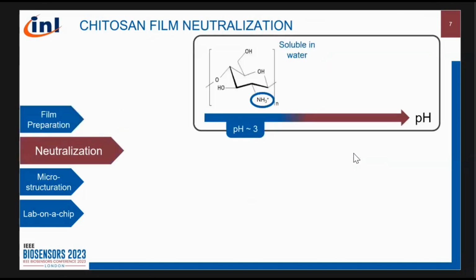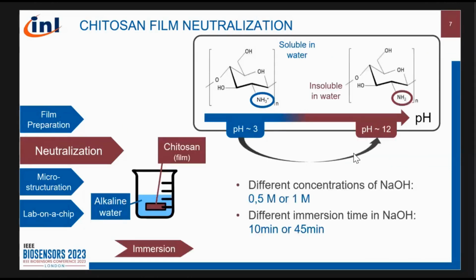Now the film, if you remember, is still soluble in water. So we need to add another step in order to be able to use it in a microfluidic system. So we use a neutralization step. We immerse the Chitosan film in alkaline water. We try different concentrations of sodium hydroxide and different immersion times in this alkaline solution to check the properties that we obtain. This will deprotonate the amino group and make it insoluble again.